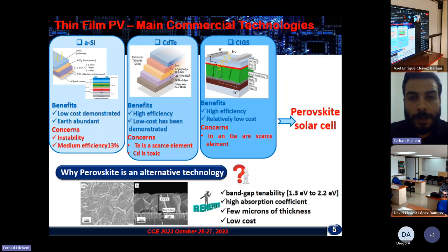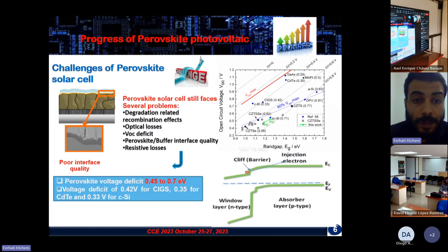Despite these benefits, several challenges are still associated with perovskite solar cells in which we can notice the degradation related to recombination effects, optical losses, open circuit voltage deficit, and the poor quality of the interface between the perovskite absorber material and the buffer layer,